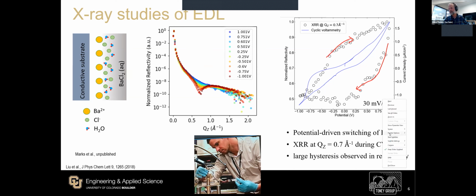I am quite surprised by this, because I would have expected, on the time scale of the measurement, at 30 millivolts per second, probably collecting for a couple of seconds, that the double layer response would be completely reversible. What we see here is a large hysteresis. We've looked at a number of electrolytes, and it suggests that some time scale associated with this layering process is actually decently slow. I would have anticipated RC time constants, which are typically microseconds, as expected for the double layer. But pretty clearly here, we're seeing a much longer time scale. And in this paper, done on some data taken by Hoyt Yu, where they did potential jump experiments on platinum surfaces, they also see time constants that are quite slow.